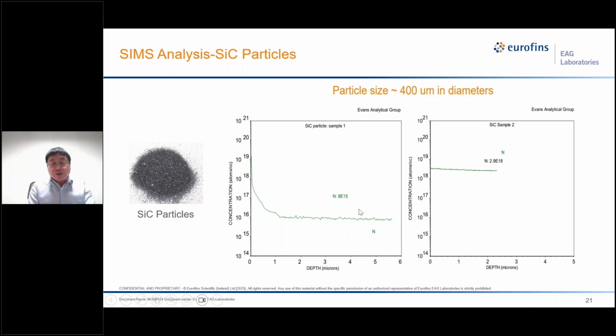This profile shows the nitrogen concentration is about 8E15 for sample 1, and for a second sample, the nitrogen is about 3E18. I want to point out the nitrogen concentration is an intrinsic property of the silicon carbide sample, so it's determined by the batch of the sample. Generally, we will measure several particles for each batch, and then get the average result.